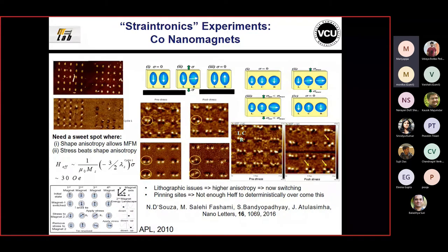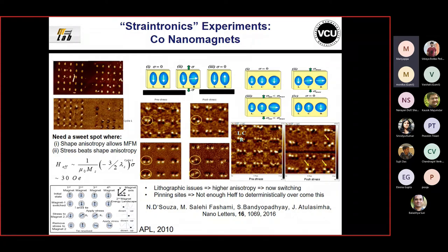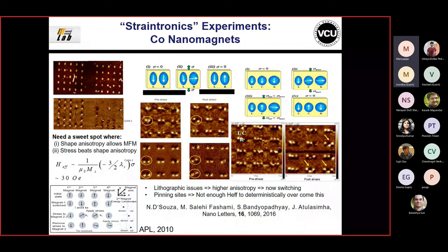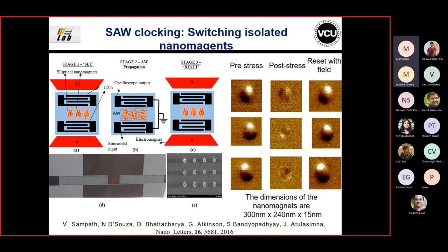You can also go to three magnets where you have most, less, and least anisotropy. In that order, this will switch the next, and that will switch the next - going from an artificially antiferromagnetic state from a down-down state. Of course, not all devices work because of lithographic issues. In terms of logic, this was interesting ten years ago, but right now CMOS performance in logic is really unbeatable because of switching errors. The probability of switching a magnet from up to down at 10^-5 or 10^-6 is not enough, because a transistor switches with a reliability of 10^-15. So this switching is not amenable to conditional logic, but it's good for memory and neuromorphic computing.